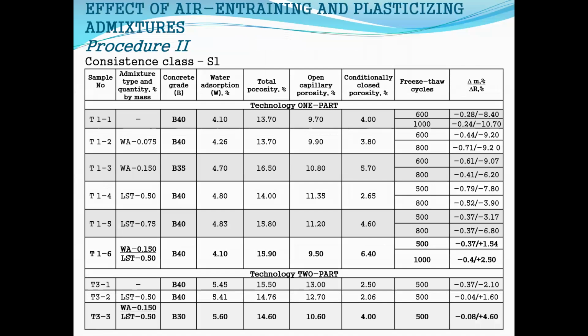Application of air entraining and plasticizing admixtures ensures higher volume of conditionally closed pores and lesser volume of open capillary pores, which increases freeze-thaw resistance when alkaline component was applied in dry as well as in liquid form.